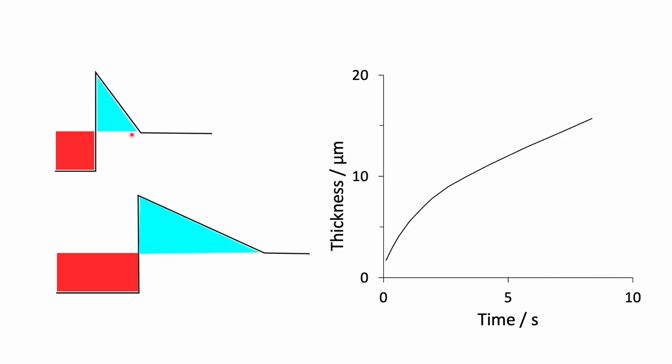So here, for example, it's quite sharp. Here it is much more gentle. So the solute has to diffuse over longer distances so that we don't exceed the concentration here, which is C_L alpha. Therefore, the growth rate slows down as the particle becomes thicker, and this is the form of the size of the particle as a function of time. So initially it thickens quite rapidly, and then this gradient becomes more and more gentle as time proceeds.